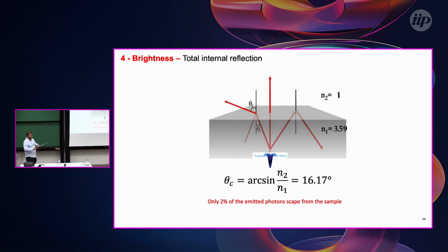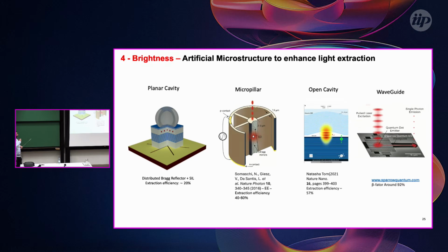Thinking about how to increase the extraction efficiency, there are a lot of methods that we can use. The first one is the simplest one, that is using distributed Bragg reflectors. Basically, this is the simplest because you can grow these mirrors in situ during the epitaxial growth of the sample, and you don't have to do any kind of device development. Basically what you do is grow these DBR pairs, and to increase the extraction efficiency, you can also use a solid immersion lens on top of the sample, and with this you can increase the extraction efficiency to 20%.